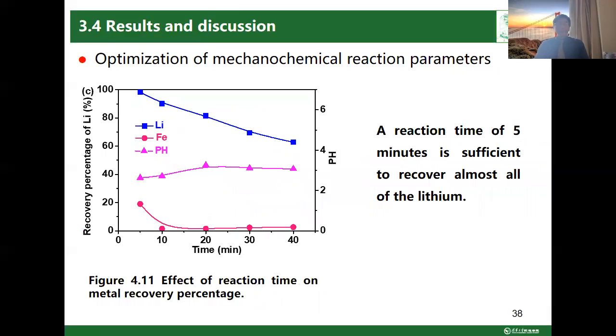This figure shows the metal recovery efficiency with different ball milling times. The result of the study shows that a reaction time of 5 minutes is sufficient to recover almost all of the lithium.